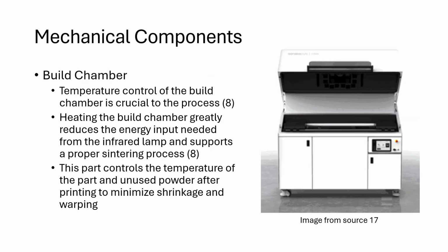The build chamber must maintain a carefully controlled temperature. Typically, it's slightly below the polymer's melting point. The main goal here is to straddle the line between the polymer's recrystallization temperature and its melting temperature. Preheating minimizes the energy the lamp must apply and prevents warping or delamination during cooling. This warping during cooling is apparent if the build chamber is not kept above the recrystallization temperature. If this happens, then the part is subject to warping due to recrystallization shrinkage.